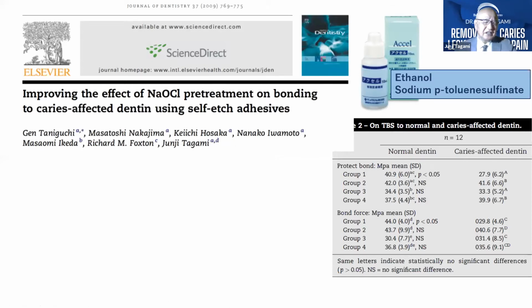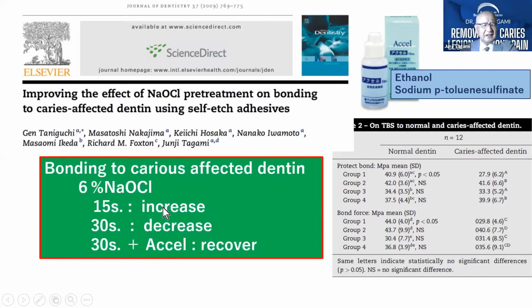In this study, we tried to improve the bonding to caries affected dentin using this kind of treatment, that is sodium hypochlorite, to sterilize and also to deproteinize the surface of dentin. Of course, if we apply a very low percentage of sodium hypochlorite for a very short period, 15 seconds, the bonding increased. However, if we apply it for 30 seconds, it decreased. And if we apply the reducing agent named Accel after the sodium hypochlorite treatment, the bonding was recovered. It's very good information for us.